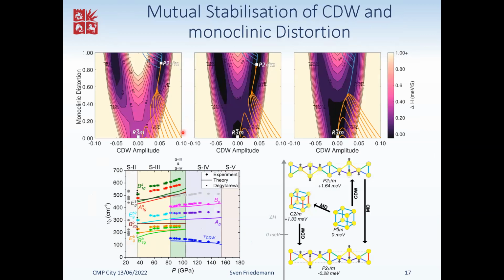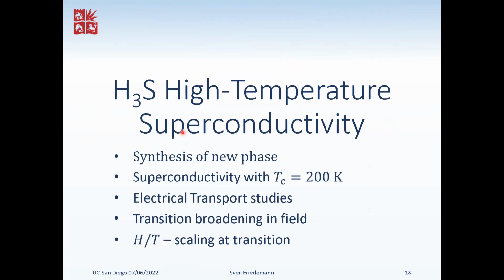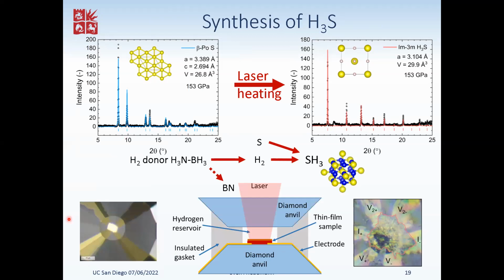Okay, so with that, I'll move to the hydride superconductors. We've done some work on hydrogen sulfide. This includes both the synthesis as well as studying the superconductivity with electrical transport measurements, including in high magnetic fields. The way we did this is by loading sulfur in a diamond anvil cell.